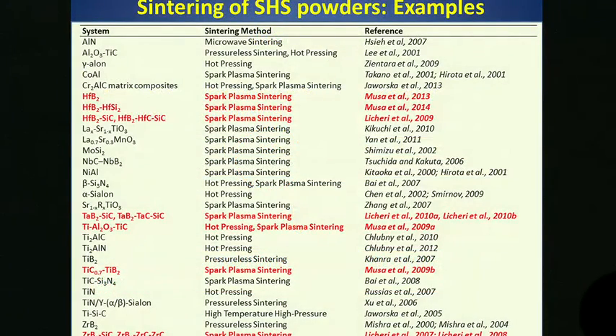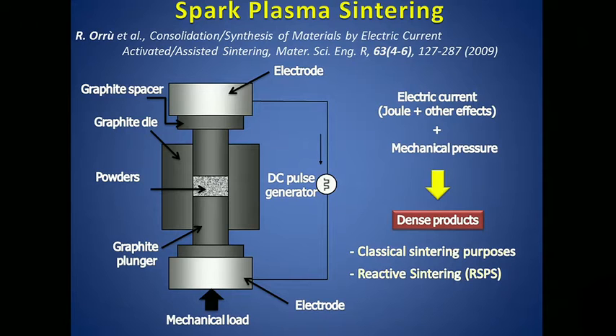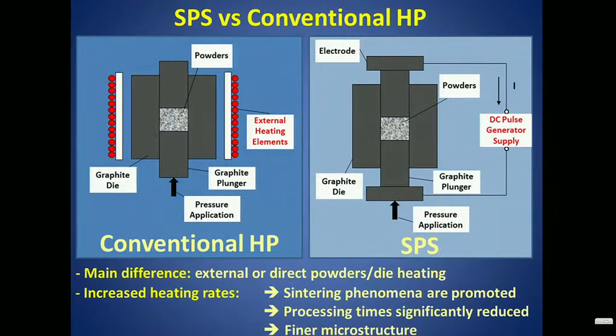There are, of course, in the literature very many applications of sintering of SHS powders, which I'm not going to go through. But let's talk about this relatively novel sintering technique, known as SPS. Basically, you let the current pass through the die, which is typically made of graphite. In such a way you can get a dense product, and you can reach classical sintering purposes, but you can also do reactive sintering. So if you compare these two techniques, the conventional